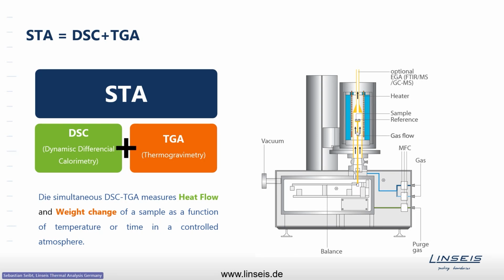The yellow part is the sensor head. As said, these are plug-and-play sensors. You can plug them in here. When the furnace lifts up and the furnace is open, from the top side you can insert a rod. And on top of the rod there is a sample holder consisting usually of a sample and reference crucible within a platinum or metal bracket or sensor head. And this is the typical DSC sensor. So the DSC signal is obtained at the sensor head, and the weight change signal is obtained out of the electric magnet down here. So that's what the instrument measures.